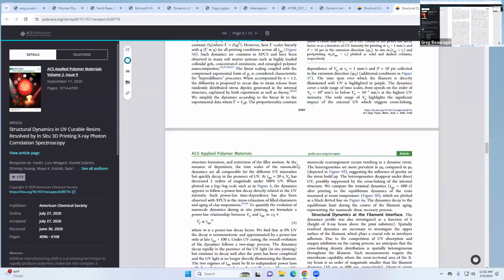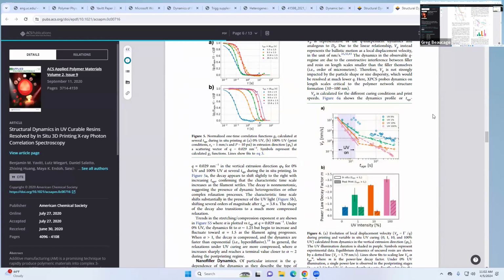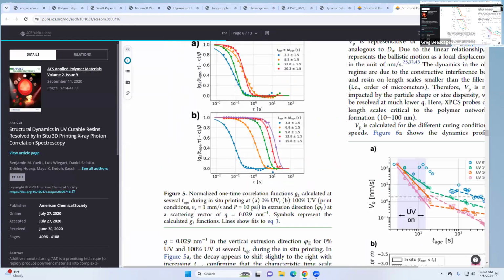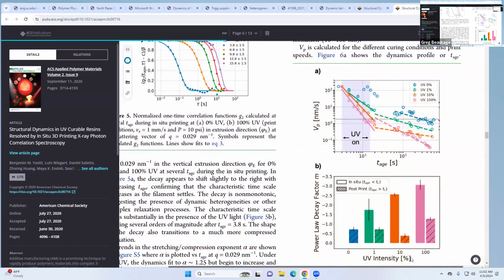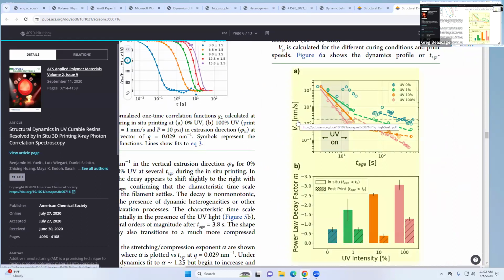Yeah, so we tracked the dynamics under UV. So we were UV curing it. We would deposit the filament, hit it with UV, initiate that curing reaction. Initially, you can see a really fast decrease in the dynamics, and it's a function of the UV intensity that we use, right? So if we cure it lightly, they'll slow down slower. If we cure it really fast and hard, they drop really quickly.